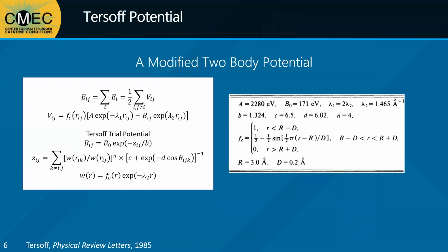Our potential of choice for our silicon simulations is a modified version of the Tersoff potential. The original Tersoff potential was initially developed for silicon and is a modified two-body bond order potential that incorporates structural chemistry into its framework. The A term here describes repulsive forces, while the B term here describes bonding forces, including the bond order and local environment. Any considerations for bond angles, competing bonds, and bond strengths are folded into this B variable.